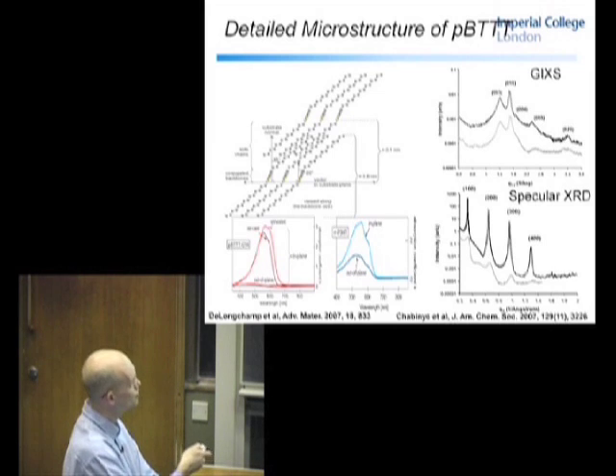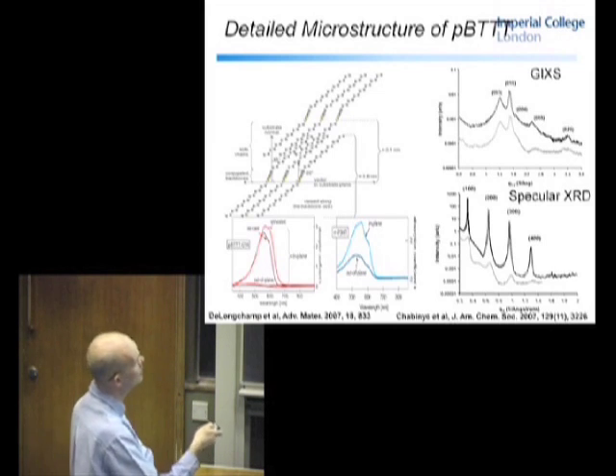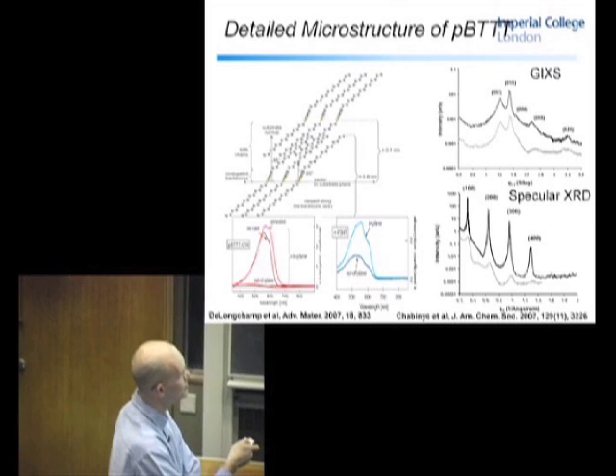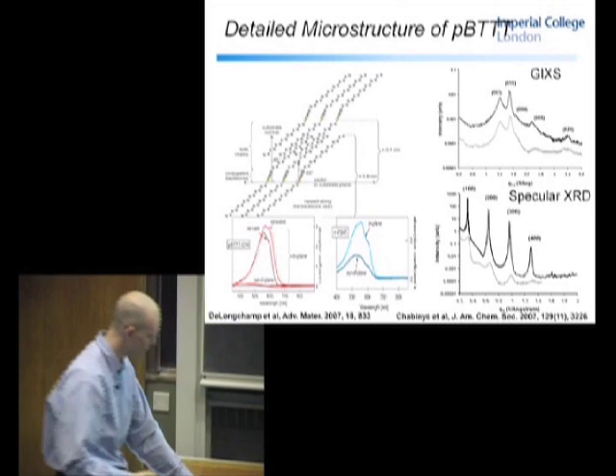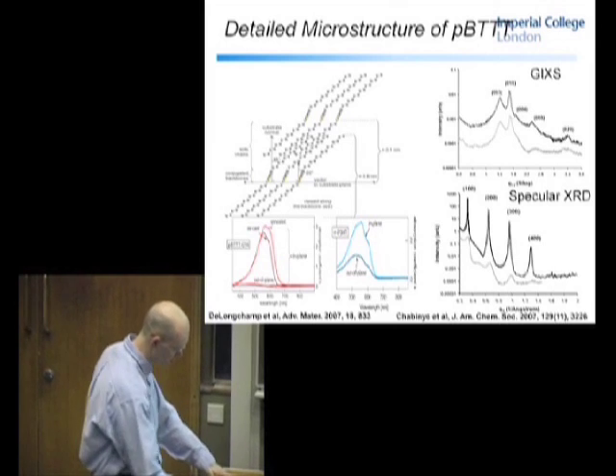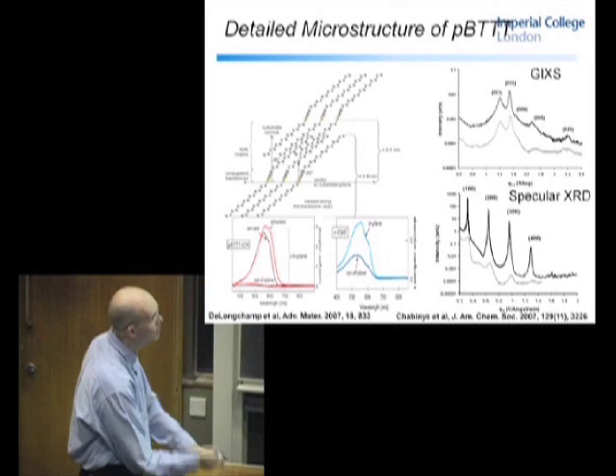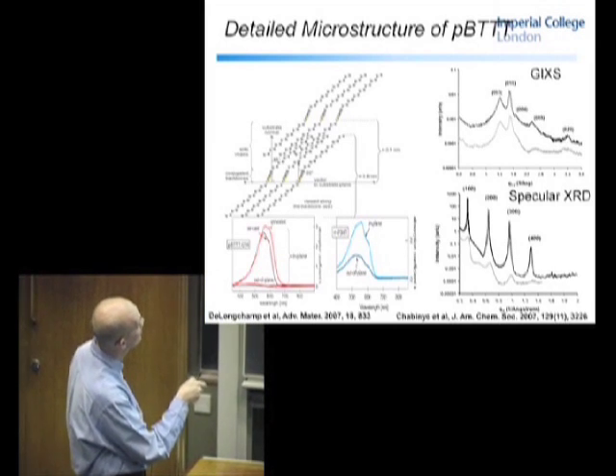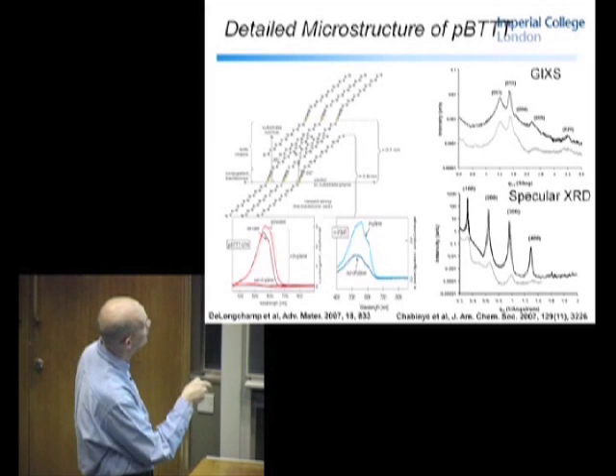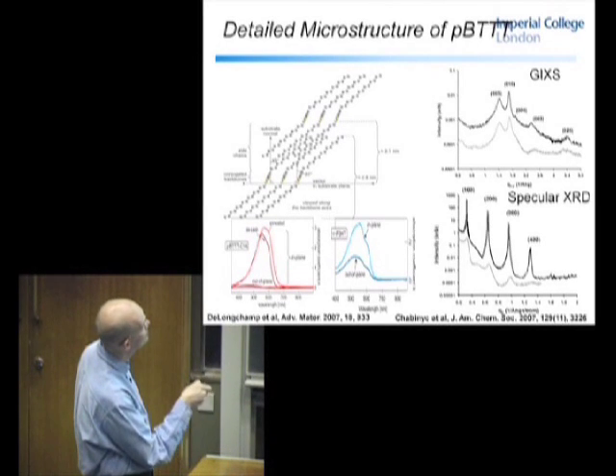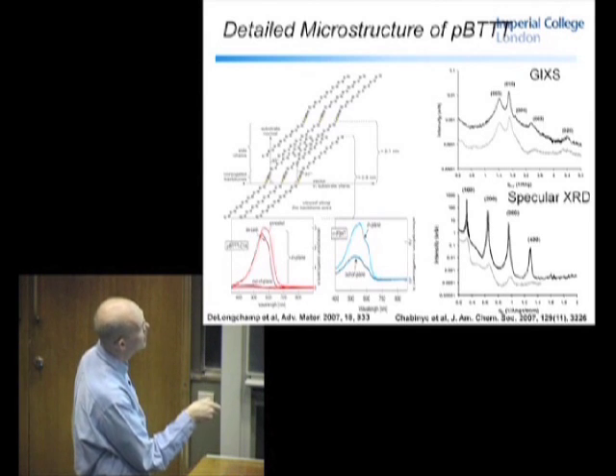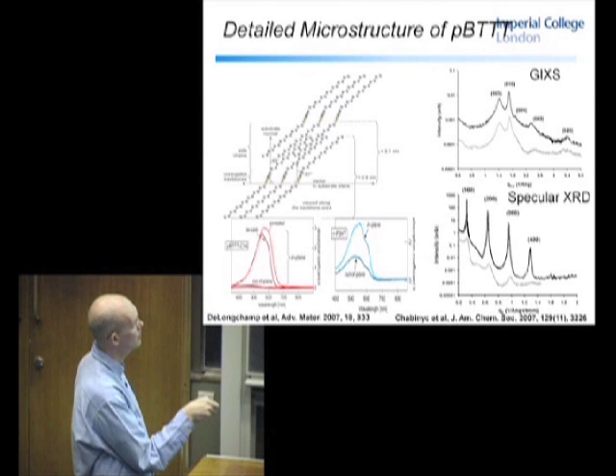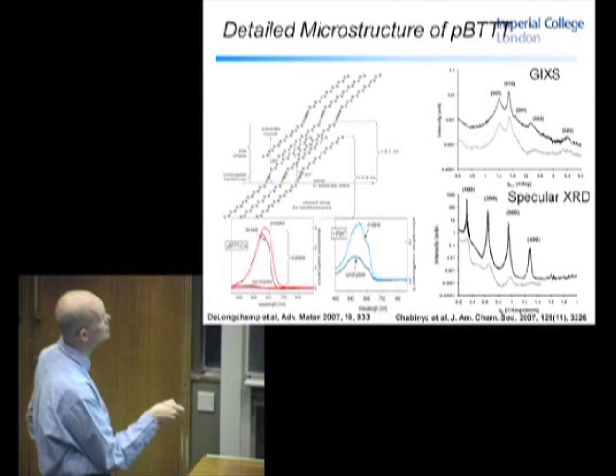And you can probe this structural order by X-ray scattering. In this case, this is grazing incidence. So if this is your film, your incident beam is almost in the plane. So it's probing this order here, so you can get what they call the 0-1-0 reflection, which is a pi-pi reflection, and you see it's very sharp. I mean, a typical polymer looks more diffuse, kind of like this. This is more or less van der Waals distance, but here you can see sharp peaks.